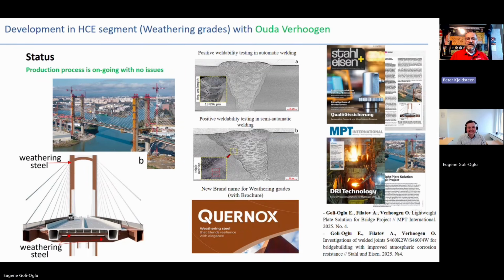And here thickness was up to 120 millimeters, I remember it. The maximum for this project was 130 millimeter plates, which were used in foundation parts, of course, to make it solid. And then in the top of the bridge, it's 10, 12 millimeter, even 8 millimeter. So like a standard, in the bottom of the construction you have thicker plates, and then you are decreasing the weight to make it stable.